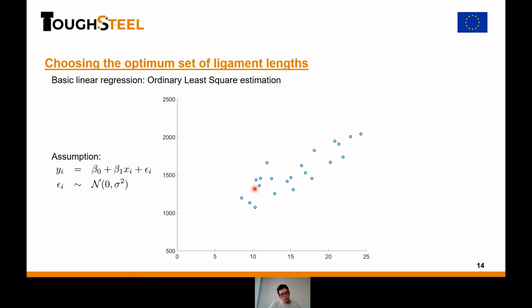But of course, we want to keep the error on the expected essential work of fracture the same or better than the equidistant case. So we need to define how we do things to be able to have a solution. For this, we need to go back a bit to how we do the linear regression. So we have a set of data points. We assume that it is linearly distributed. And so we have our two parameters here for the distribution and some white noise that explains the variance in the data sets.